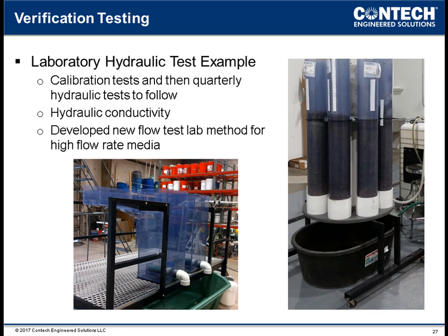Hydraulic verification testing should also be performed to ensure the permeability criteria is met. Just as an example, each new Filterra media batch receives hydraulic column tests during blending to ensure the design flow rate is being met. Quarterly hydraulic testing is conducted thereafter on the stockpiles being used to verify flow. Hydraulic conductivity is measured rather than just infiltration rate because it's a more conservative approach to flow rate measurement.